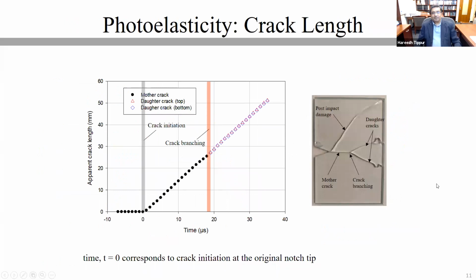So I'm going to not focus heavily on the contact stresses themselves, but focus more on the crack problem. Here, the crack length is plotted as a function of time, crack length history basically. And the gray bar that you see is the crack initiation place, and crack branching corresponds to the red bar that you see there. The solid dots represent the mother crack that is propagating as a mode 1 crack, and then once it branches, it becomes mixed mode crack. The fractured sample is shown on the right hand side.